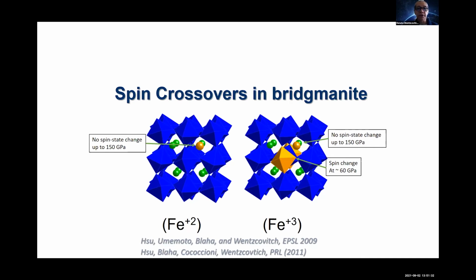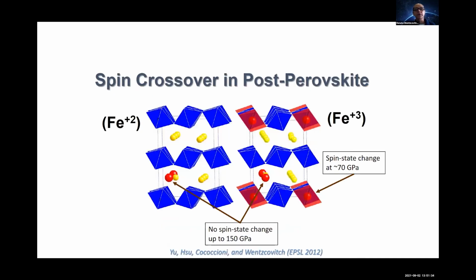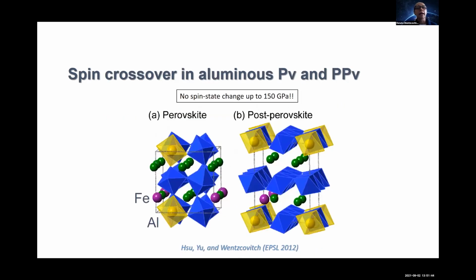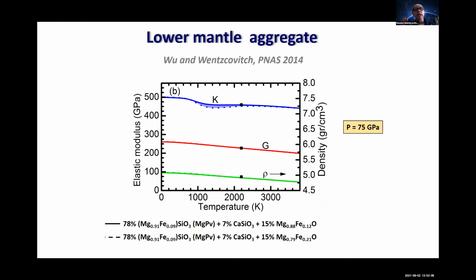In the A site, no spin transition in ferric iron either. Post-perovskite, the same. The large site, no spin transition in ferrous or ferric iron, spin transition only in ferric iron in the small octahedral site. Aluminum is a poison for the spin transition. Aluminum kicks iron out of the octahedral site, and no spin transition. For us, it's a blessing because it makes easier, in many respects, calculations of velocities and analysis of the lower mantle. But that's not the end of the story, of course.